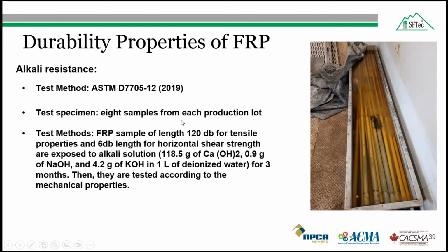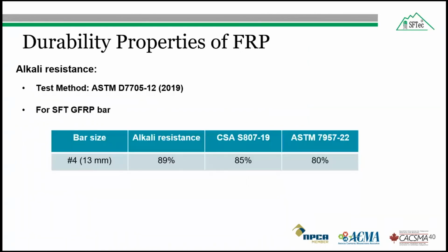So generally what we see here is how much strength they lose after the exposure to the alkali solution. For the SFTec bar, the average alkali resistance value was around 89%, which was greater than both CSA S807 and ASTM D7957. And here you can see the CSA code is more strict. It provides a very high value of 85%, whereas ASTM provides only 80%. So these are all the properties we test for the qualification test.